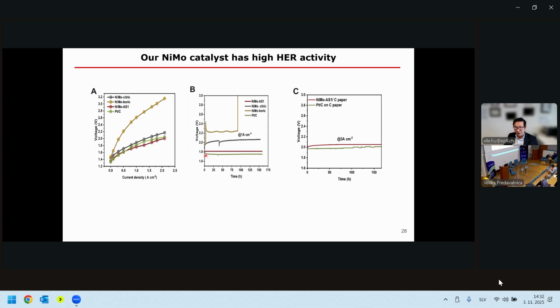If we put it into an electrolyzer, an AEM electrolyzer at 1 amp, again, here platinum is slightly better, but we are also quite good. We can also do it at 3 amp, and again, it's quite similar to platinum in these kinds of devices for the 50 hours.